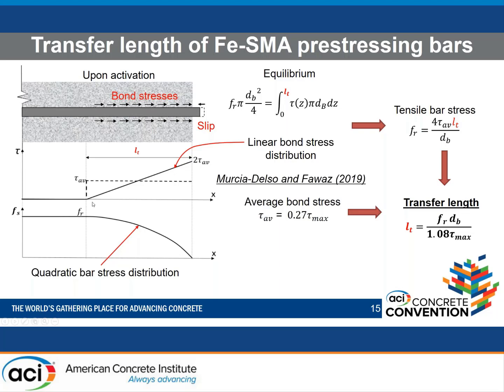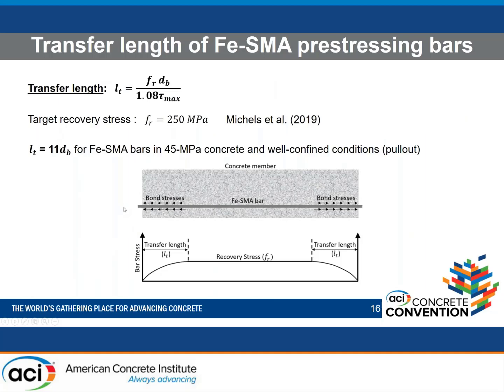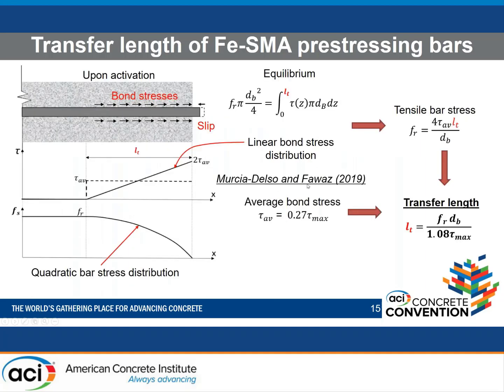And as you see here, the linear distribution is going from, because it's linear and the end bond stress is 0, so we have 2 tau average, and this is tau average. And with the same model, it was recommended by Murcia-Delso and Fawaz that the tau average is 0.27 tau max. Plugging the tau average in this equation, we get a transfer length equation, which is a function of the target stress, the bar diameter, and the maximum bond stress of these rebars. Here, by the way, I'm showing the bar stress distribution, and based on a linear bond stress distribution, we get a quadratic bar stress distribution.